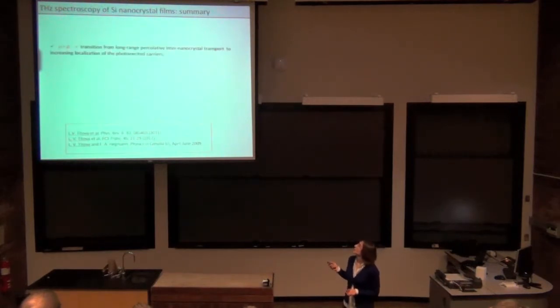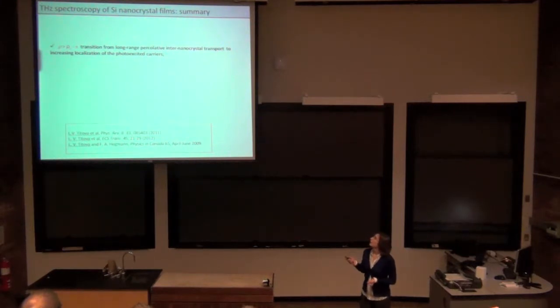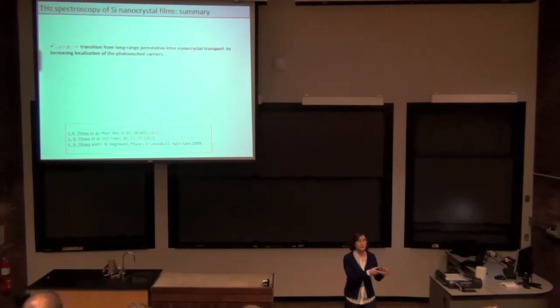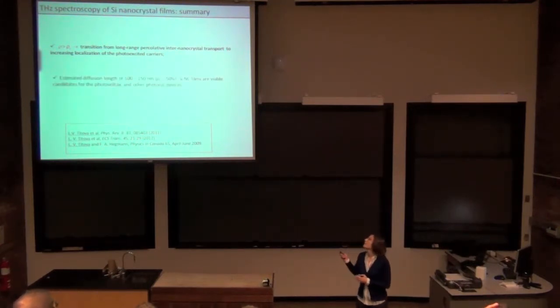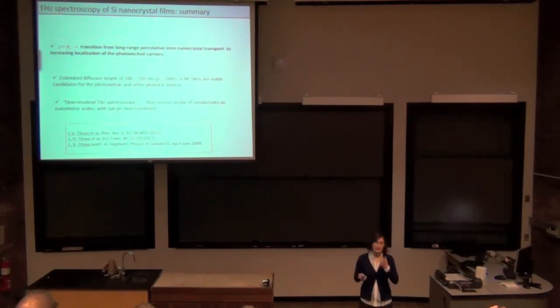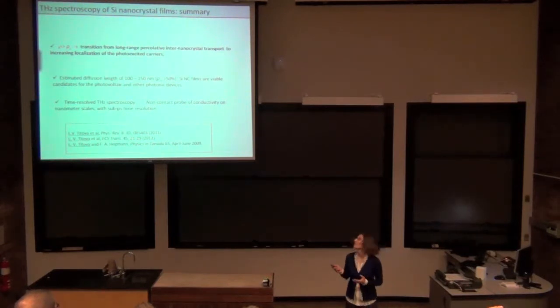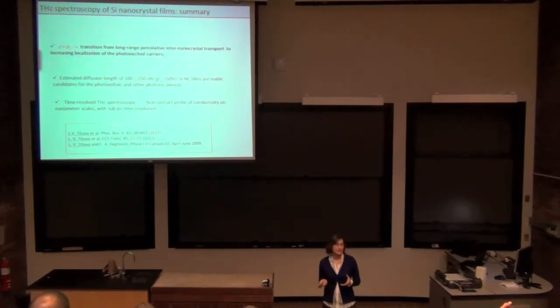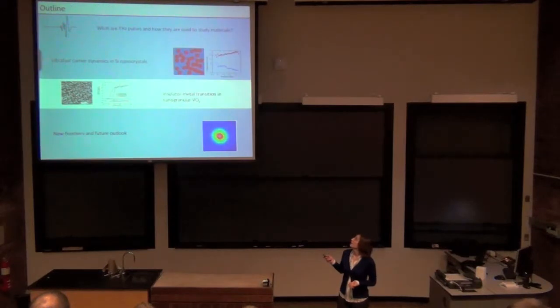So just to summarize this work, for the silicon nanocrystal film, what we see is a transition from long-range conduction at early times after photoexcitation to enhanced localization at later times. We also estimate the diffusion lengths, and hopefully I'm starting to convince you that terahertz time-resolved spectroscopy is indeed a very useful tool to study conductivity in nanomaterials without the need for contacts. Now I'm going to tell you about